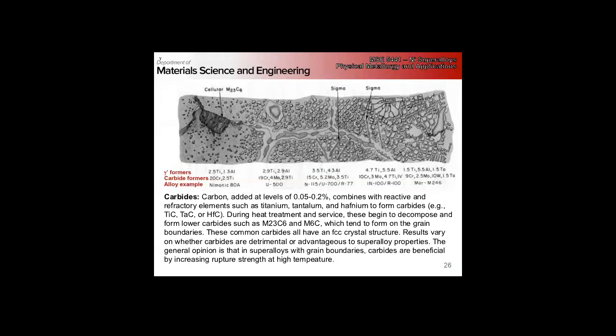Carbides in single crystal alloys are, of course, going to be bad because then they're an inclusion. The carbides tend to be cubic and have derivatives of the FCC structure, either the M23C6, metal 23 carbon 6, or metal 6 carbon type stoichiometry.